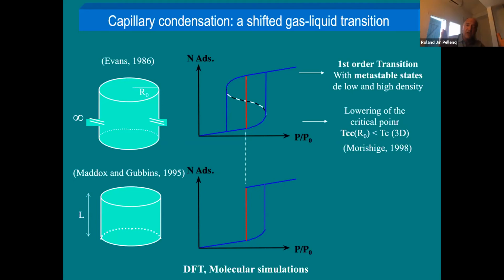The desorption line corresponds to something called cavitation—you break the liquid, depressurizing it to a point where it breaks. But Maddox and Gubbins showed that if the pore system has a finite length, which is the real case, the desorption occurs at equilibrium, and you don't see this cavitation—you go through the equilibrium instead.